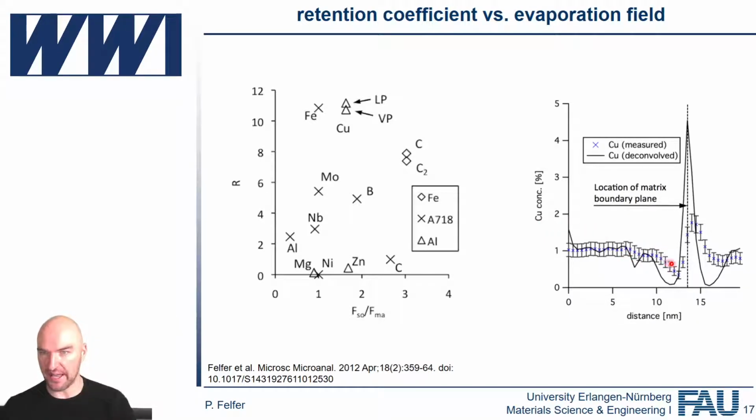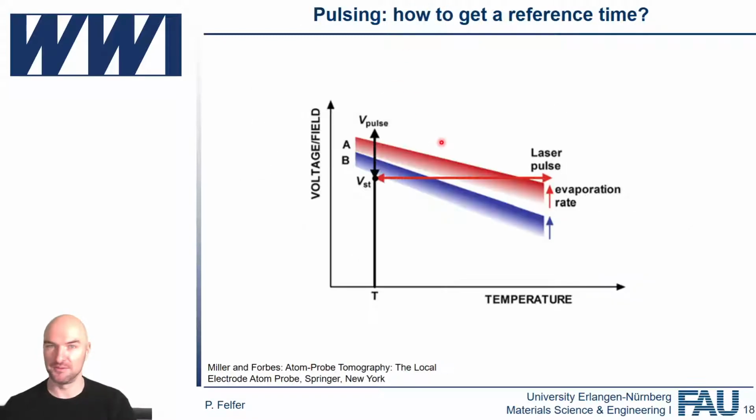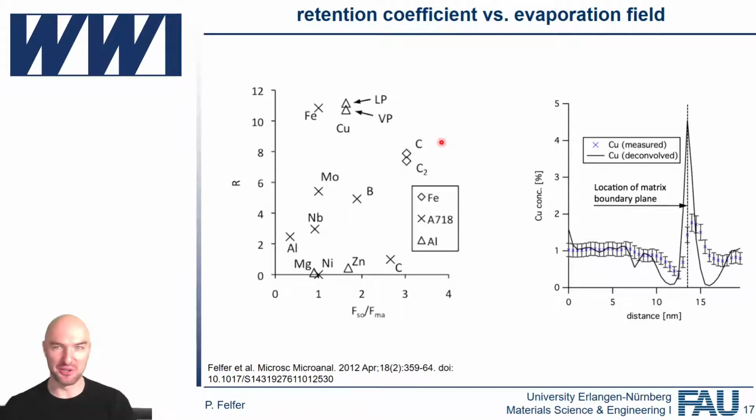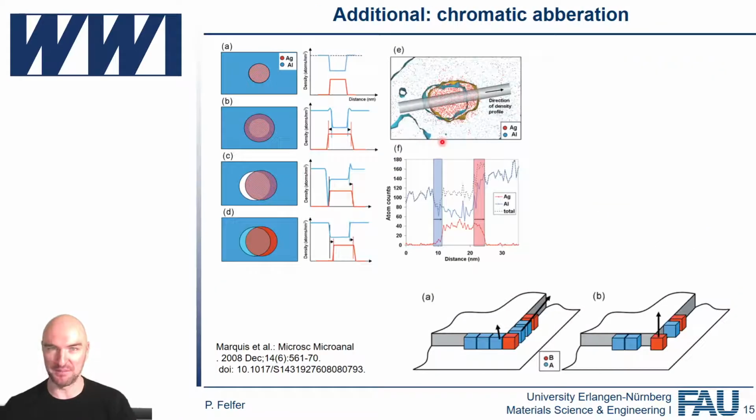But if we just count how many atoms are there that wouldn't be there if the interface wasn't there, that's a much more robust value. That's why we are going to be looking at interfacial excess values and interfacial excess mapping tomorrow on Friday, simply because concentrations at interfaces are not a particularly representative value. If you interpret a lot of that, you might just be chasing ghosts. Okay, so there was a lot of information about what can go wrong.